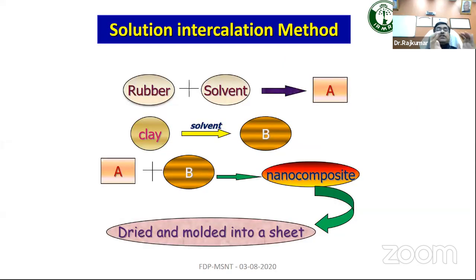In the solution method, rubber is taken with a solvent and they make the solutions, and then put the nanomaterials in, for example in the same solvent used for clay or any nanomaterials. Now the nanomaterial solution plus rubber solution is mixed, then dried, cast and made. So this is all practically possible at lab scale, but it's not possible at industrial scale because so much solvent will escape. What is found in academic research is that using the solvent, you are able to incorporate nanomaterials into the polymeric matrix. Wow, wonderful.